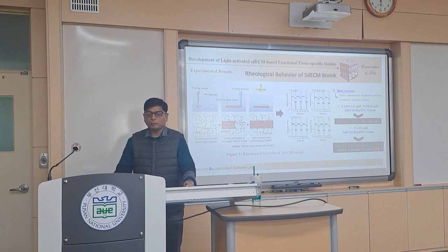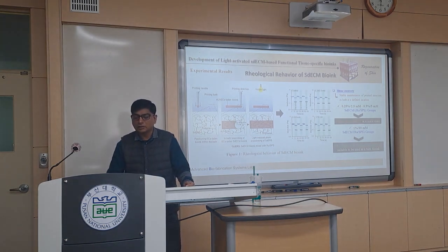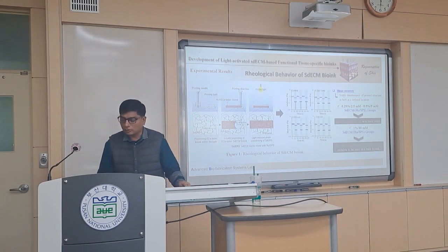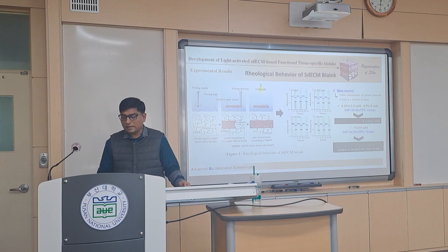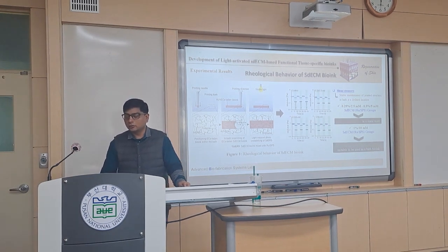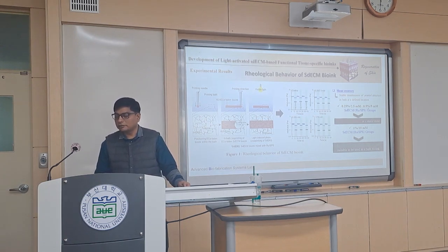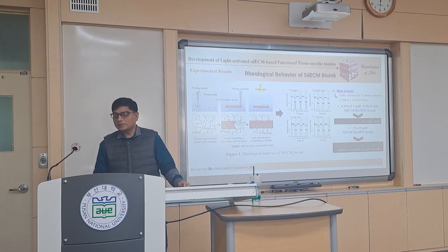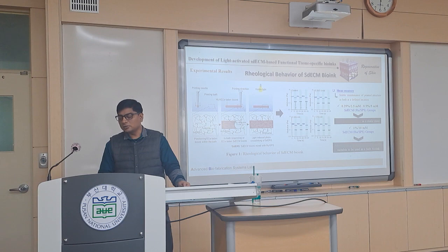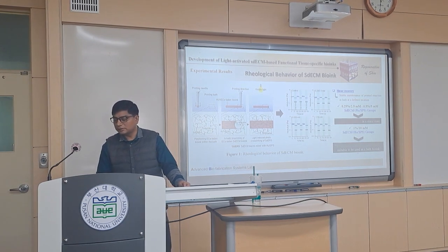The experimental result is the development of light-activated dECM-based functional tissue-specific bath. First is the rheological behavior of dECM. We use three different concentrations of the bioink: 0.25, 0.5 and 1. We get shear recovery, meaning stable maintenance of the printed structure in the bath at the defined location. The 0.25% to 0.5% dECM groups were structurally unstable in the static state, and the 1% dECM group maintained rheological properties suitable to use as a bath.